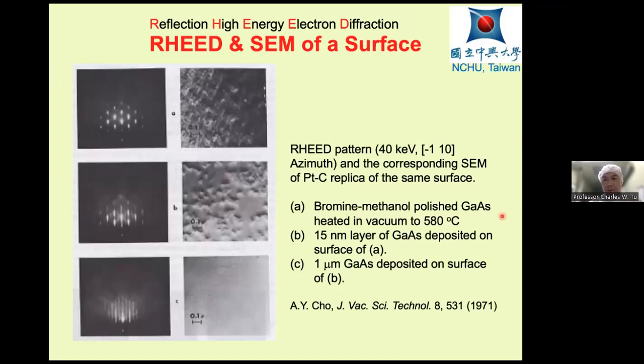This slide shows that when we polish a gallium arsenide surface with bromine methanol, and then heat it in vacuum to 580 degrees, supposedly the oxide is already dissolved and the surface is clean. The sample is then cooled down, taken out, and a replica of the surface is made. We look at it with SEM here, and on the left is the electron diffraction. Here we see that the surface is rough, and so we see a three-dimensional electron diffraction.